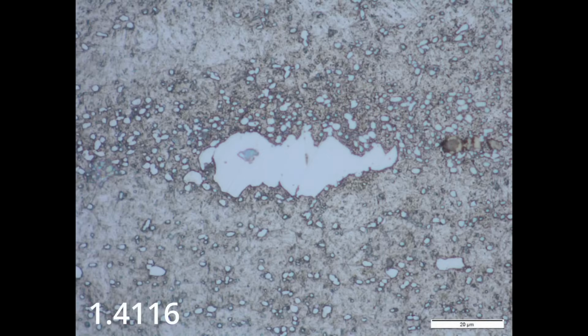Another thing is you can't just get rid of them with higher temperature. So if you heated the steel to just under melting, those large carbides would still be there. They are very difficult to get rid of. They're very stable. They don't go away. And then if you melt it and then resolidify it, those carbides just form again in the liquid because they want to form according to the composition.